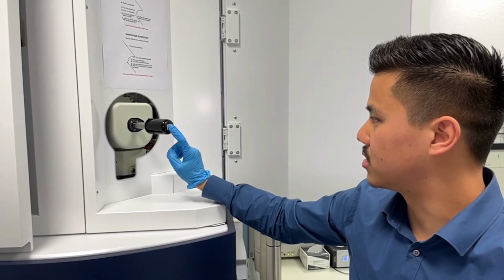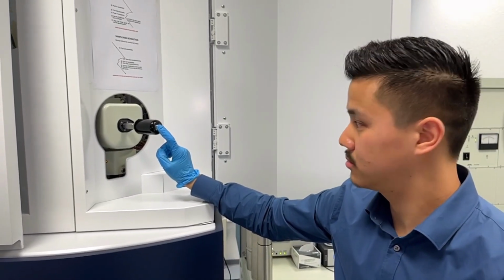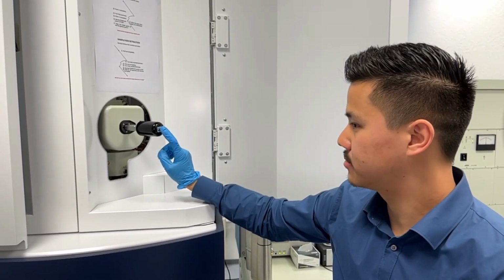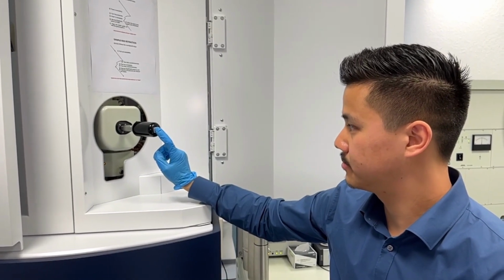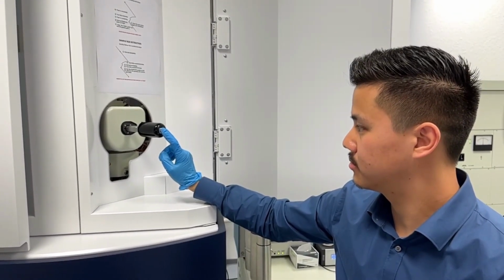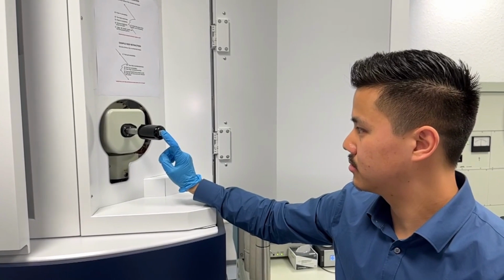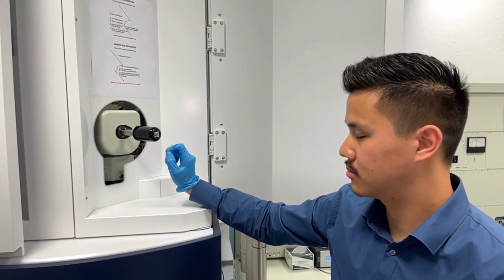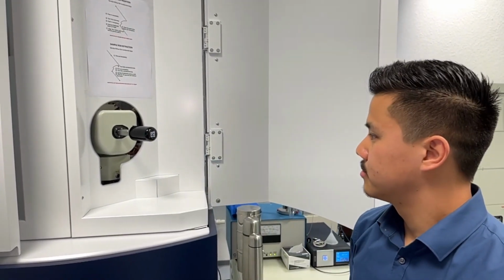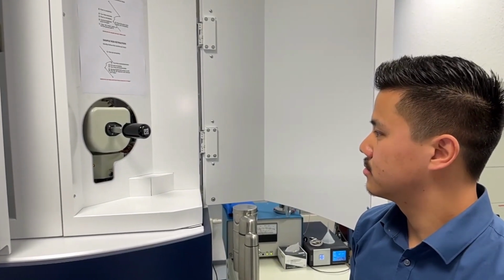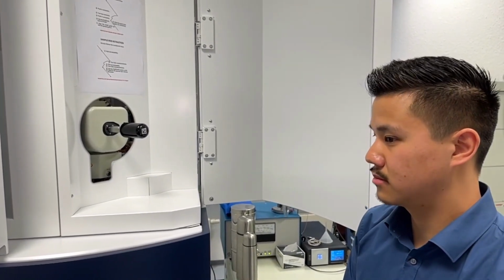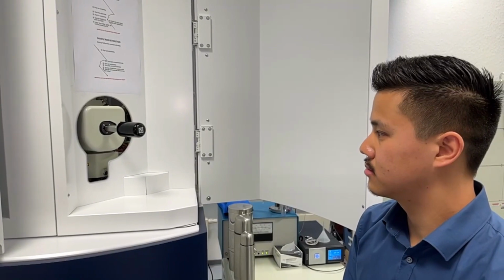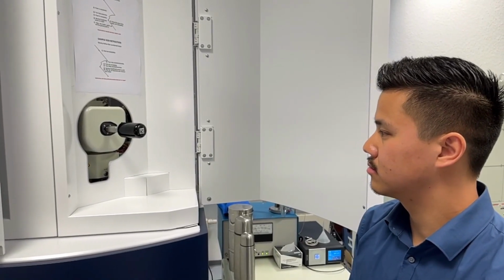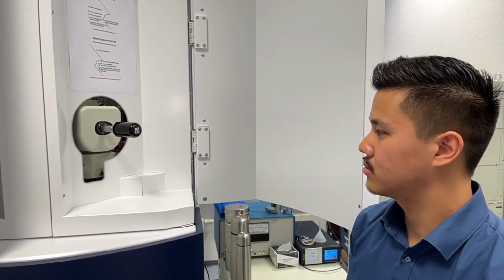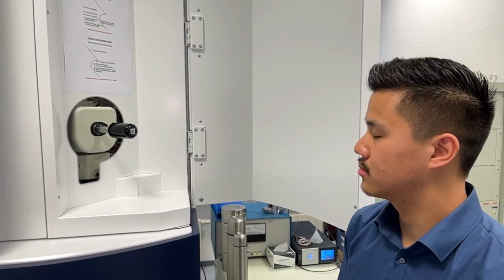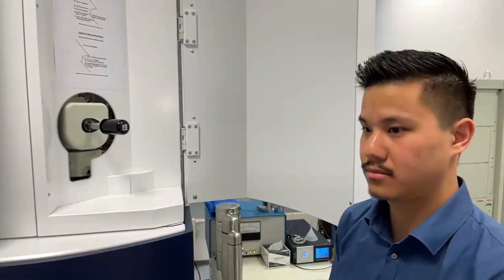the environment. The sample is now sitting in an airlock chamber, so we don't put it directly into the vacuum of the diffractometer, because then we'd have to break it every time we put in a sample. Instead, there's an airlock mechanism, so now it's in a pre-evacuation chamber, which will then pump down right now, and after it has pumped down, which typically takes a few minutes, you can fully insert the sample into the vacuum.